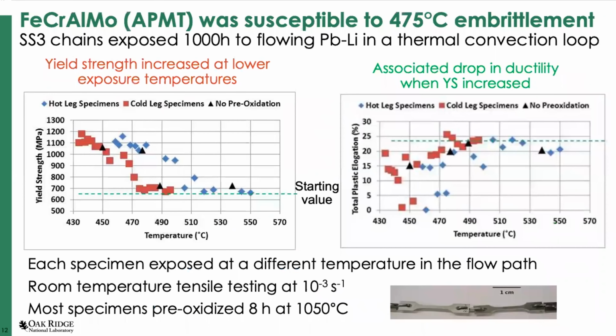And another test where we did see some results is this experiment for the fusion energy, where we had a chain of specimens in flowing lead lithium, and you can see the temperature range that these are exposed at. And when we break them afterwards at room temperature, you can see that we've had a strong increase in the yield strength and an associated decrease in the ductility. And this is a typical 475 degrees C embrittlement, but able to measure that using these type of tensile specimens.